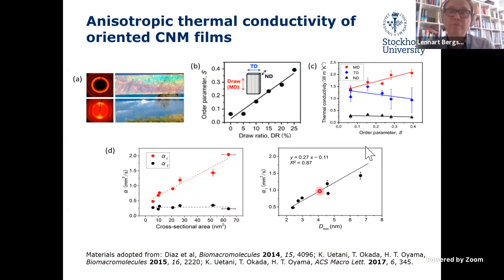This final figure shows the effect, in this case, of the diffusivity, how that changes as a function of diameter, showing that we can get a very high degree of anisotropy in films of the heat transfer, up to a factor of 8, which is basically the theoretical limit for a single fibril.